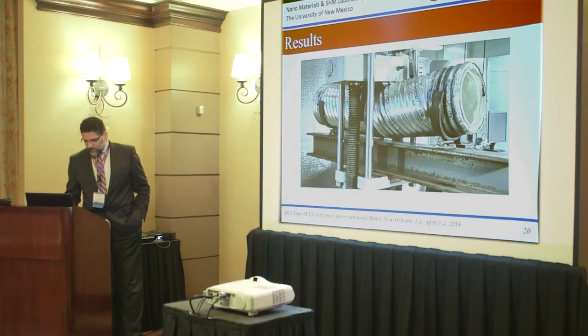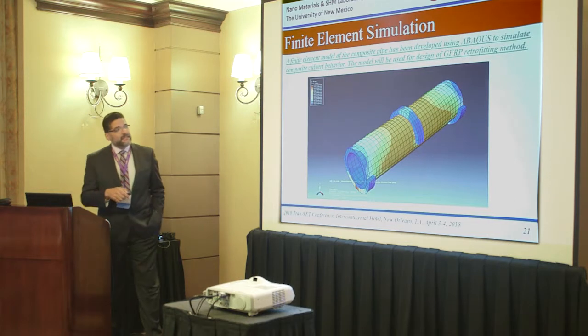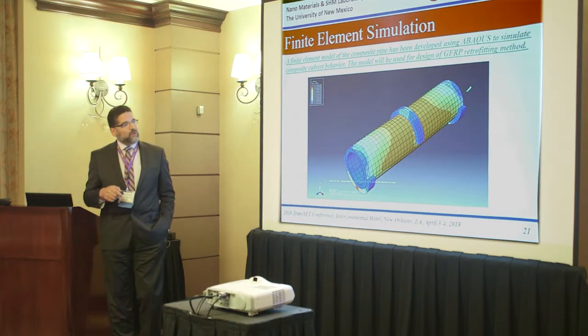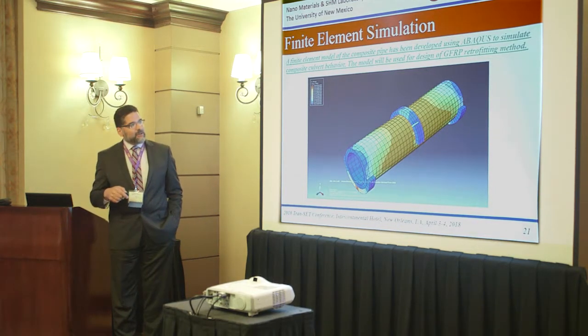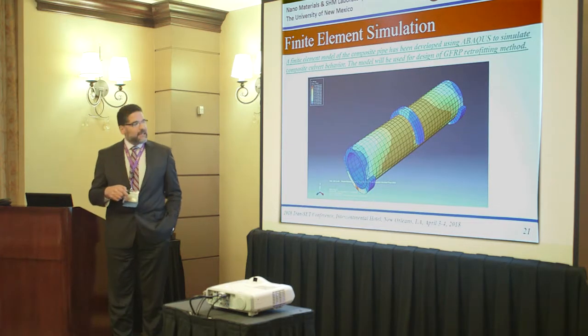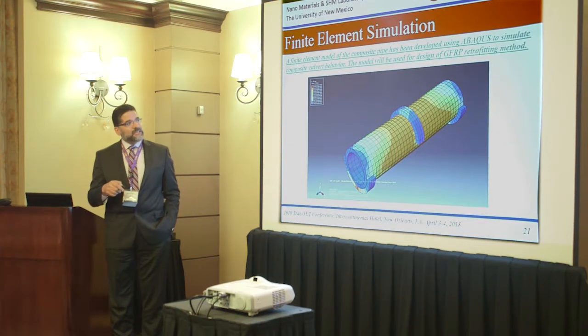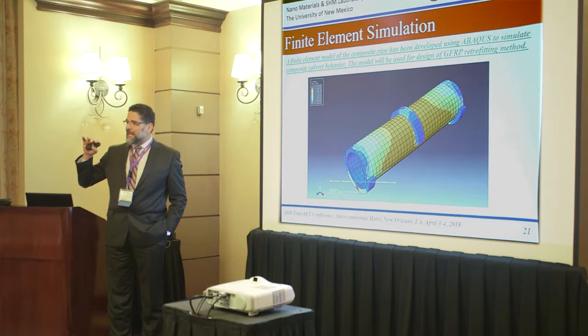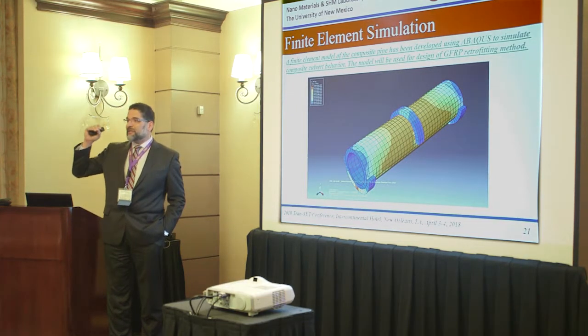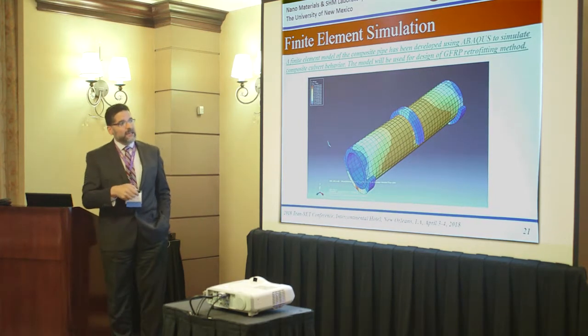This is again the deformed shape, and this is the finite element model we developed to simulate the behavior. Our objective of using the finite element model is to use it to design the GFRP. We use Abaqus because that allows us to design the glass fiber with the different layers. We can set the layers and the direction of the filament winding for design.